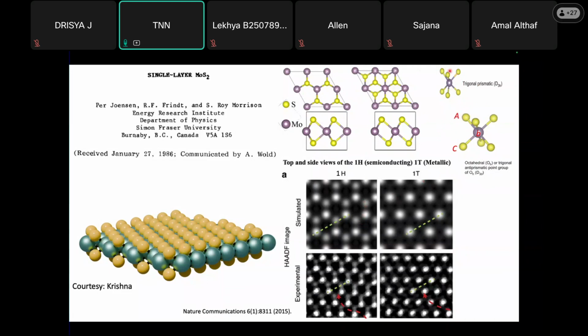Because you see here, as I mentioned, if you turn the two sulfur layers on top of each other, here one sulfur layer is not on top of the other sulfur layer. So this is called 1H MoS2, as I am going to talk about more in today's talk. And this is called 1T or 1T prime MoS2, which is actually a distorted octahedron. So this sulfur layer is not on top of this one.